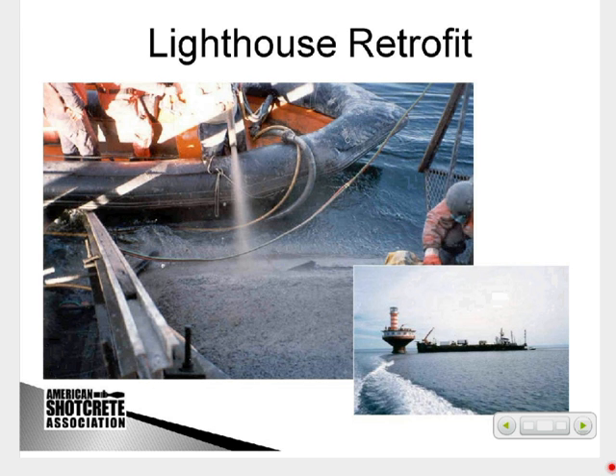Shotcrete is easy to apply to an unusual shape. On this particular picture, the inset on the lower right is a lighthouse that's, I think, in the Bay of Fundy up in Canada, where they have very high tides, and it was very impractical to come in and recast the foundation for the lighthouse. So the repair was done with shotcrete. This used an accelerator, and I think it also used silica fume to get a very quick set on the shotcrete, so it could be placed as the tide was low and rehabilitate that surface without any formwork. Basically, the surface was prepared, and when the tide was low, it was washed off and then shotcrete was applied.